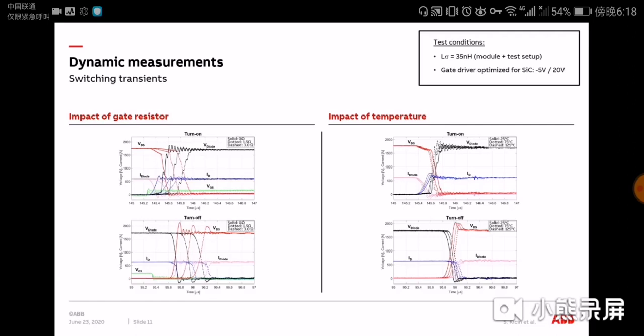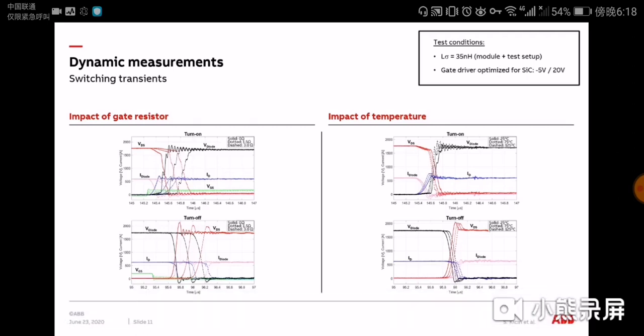The figures also include switching transients of the body diode, which, to the authors' knowledge, are the first published for a 3.3 kV silicon carbide high-power module. The diode's transients showed both expected effects, a higher reverse recovery peak as a result of higher junction temperature and as a result of a lower gate resistor. However, the impact on turn-off losses was not as significant as reported in literature. In our opinion, results indicate that the use of the body diode would be suitable for high-power modules. A more detailed analysis of switching performance of the module can be found in the paper.